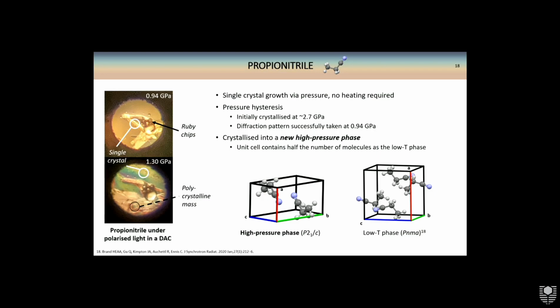And as we were getting towards the end, we could physically see the crystals starting to melt, so we were able to catch the melting partway through, increase the pressure slightly, and go back and forth a bit until a single crystal was actually caught. It's a bit hard to see because something else got trapped in the diamond anvil cell as well, but it wasn't crystalline, so it didn't matter. And that is the single crystal, which we were actually able to characterize, even though there's a bit of a mess of this polycrystalline mass down the bottom.